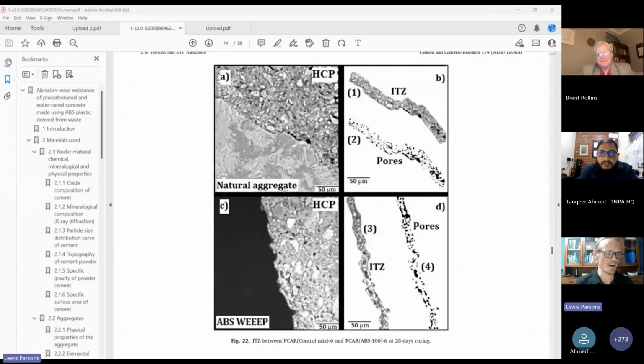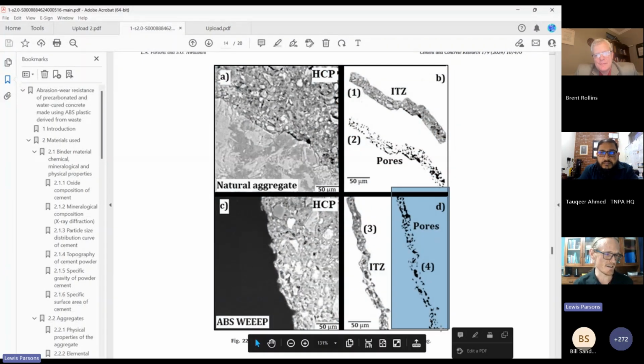Okay? Yes. So I think, just to go with what was being said, at the bottom we have a BSE backscatter electron image. The brighter points that you see here are unreactive cements, while the darker points are pores. And if we segregate the pores, we can clearly see that utilizing these plastics does result in higher porosity at the interfacial zone compared to what we find with our pastes. Now, indeed, that could happen, and we can have some refinement.